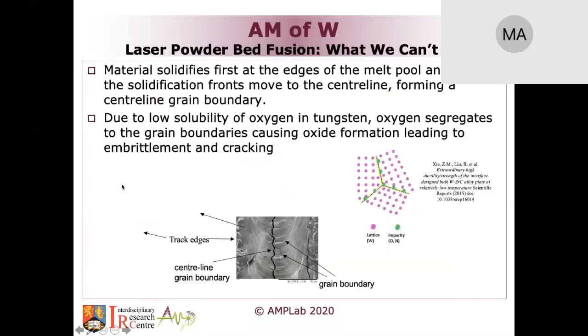So why did people find, in the early studies, specifically in the case of powder bed fusion, that the material cracks? The main theory comes from the fact that when the material solidifies, typically the solidification front would move, and because oxygen has a very limited solubility even in tungsten, the oxygen is going to be segregated to the grain boundaries, or segregating, in this case, as you can see, into the center line of the melt pool. Oxygen in that case acts as an embrittling element, and it will crack the material. That was what many people found, that the cracks happen along the grain boundaries. The main reason is the oxygen. When you have oxygen inside the material, that will eventually lead to crack formation along the grain boundaries. And as you can see, the cracks propagate in such a way that they are all intergranular cracks.